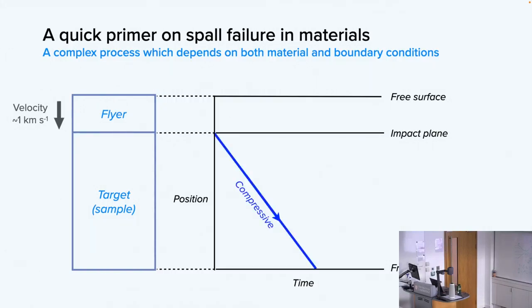So the first thing that happens is the impact of the flyer on the target causes a shock wave to propagate from that impact plane down toward the bottom of the sample. And then in time, we watch it go like this. Of course, the slope of that line is related to the speed of that wave.